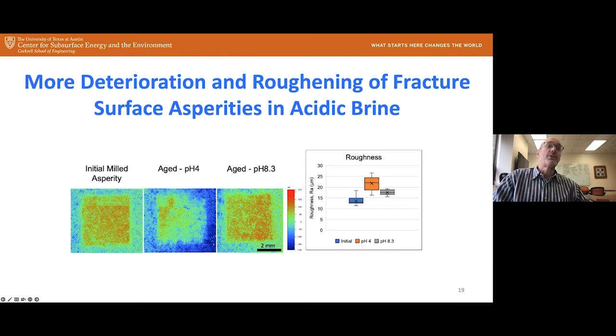So this is the initial milled asperity. And then at the end of the experiment, after this 7 days of flow and strain release, we looked at the asperities that were in contact with the pH 4 brine, flowing brine through it, and those in contact with the pH 8.3, or reservoir simulated brine. And what we found, just visually, is that these asperities that were in contact with each other at lower pH were more degraded than at higher pH.